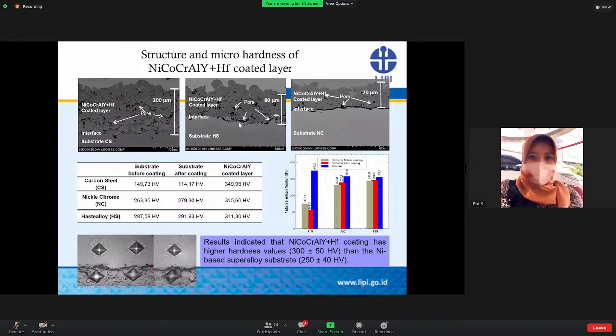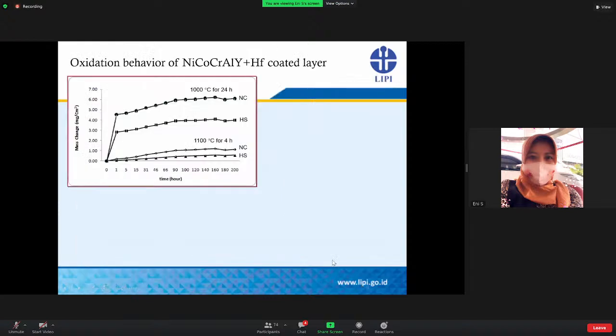This figure shows the hardness of the coating on the substrate, measured along the cross section at 3 points, and the hardness is averaged. The hardness data is compiled in this table and plotted in these figures. This is about 300 plus for the coating, with the hardness of about 250 plus minus 40. Oxidation behavior of nickel, cobalt, chromium, aluminum, hafnium will be described.